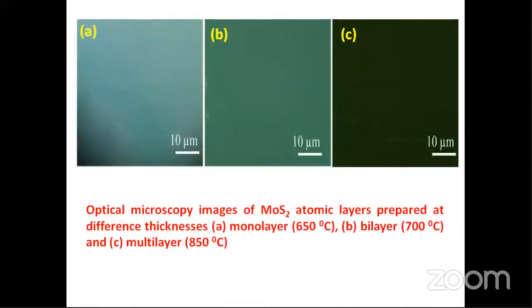And this is the optical image of the MoS2 film layers deposited at different times and different temperatures. Initially we found that the monolayer film was observed at 650 degrees centigrade, bilayer at nearly 700 degrees centigrade, and multilayer film at 850 degrees centigrade. For this confirmation, we took Raman measurements and also XRD measurements.